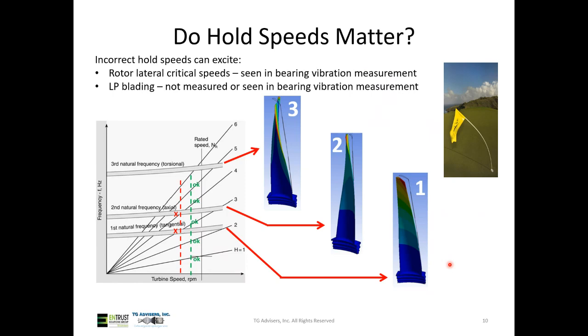And the reason for that is on most units, the last stage or the last couple stages of low pressure turbine blades are tuned. And what that means is that we selectively control the mass and the stiffness such that their natural frequencies, that they're going to vibrate at, do not correlate to a multiple of running speed. If we have a blade vibration frequency that's equal to a multiple of running speed, the blade is going to fail rather quickly from high cycle fatigue.